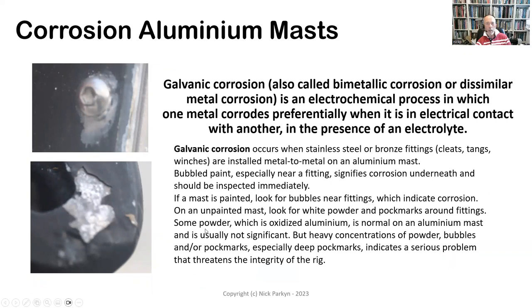We find that aluminium masts are often painted because the typical approach is you either anodize, but a lot of anodizing tanks are not big enough to take very long spars. So the next thing to do is to paint those spars. And then you tend to find that moisture will find its way in behind the paint, especially where it's drilled for fastenings and things like that. And then, of course, the corrosion starts and needs to be carefully inspected to see to what degree it has occurred, and then to repaint that area and make sure that the corrosion will not continue.